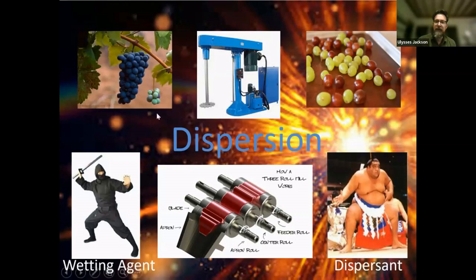So we generally will make our dispersion and then we'll mill it on a different, either 3-roll mill or basket mill. And that will give the primary particle, which will give you the strongest tint strength because the pigment particles are spread furthest apart. And then you'll stabilize that dispersion using your surfactant package. Some milling equipment can actually overmill pigments, and that can affect light fastness. If you grind an organic pigment past its initial primary particle, you've now made those crystals smaller, and you can see a drop off in light fastness.